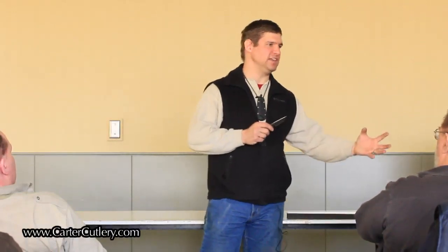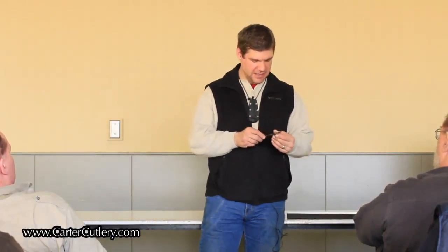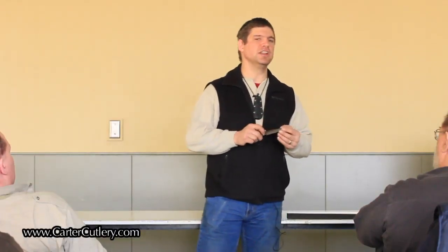Well, suffice to say that in North America, because it's more logical to grind metal while it's still soft, most of the shaping of a Western knife happens prior to heat treat. And typically, Japanese blades are left fully thick and then heat treated. That's a tremendous difference, because in the quenching process, if you have a blade with a cross-section where it's thin on the edge and thick in the back, you're limited in what kind of quenching process you can use, where you heat the blade up to a critical temperature, orange looking in the dark, and cool it rapidly. You can cool it in air, oil, water, or brine.